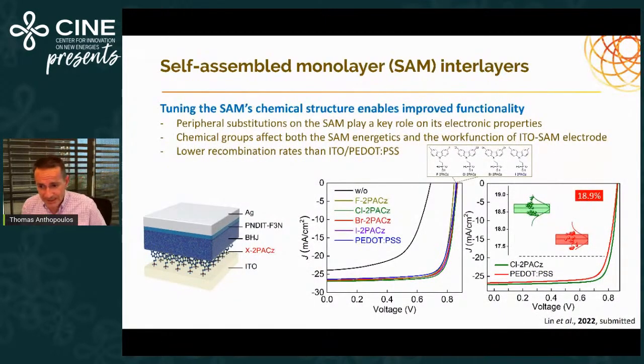And this is some of the latest data that has been submitted recently. What you see here is a number of other self-assembled monolayers where we start changing the periphery of these SAMs, and we see a dramatic impact on the overall performance. Now we're at a point where we're very close to 19%, but most importantly, we see that there's a big difference in the statistical distribution of the performance of the devices the moment we shift from PEDOT:PSS to SAM-functionalized surfaces. And you see the chlorine-based 2PACz is one of the hero SAMs we have right now, and appears to give the best results with specific organic bulk heterojunction systems.